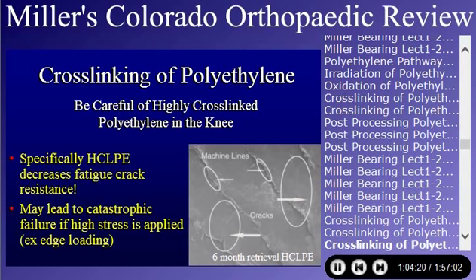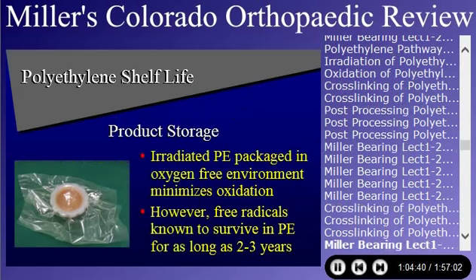So remember that oxidized polyethylene has reduced mechanical properties, but also high cross-linked polyethylene does too. The difference between the two is the wear resistance. Oxidized polyethylene doesn't wear very well, whereas highly cross-linked polyethylene wears real well in the simulator and in vivo. That's the difference between the two. Okay. The last thing we need to talk about is product storage. Irradiated polyethylene packaged in an oxygen-free environment minimizes oxidation, and that is good. However, it has been known that free radicals can survive in polyethylene for as long as 2 to 3 years.